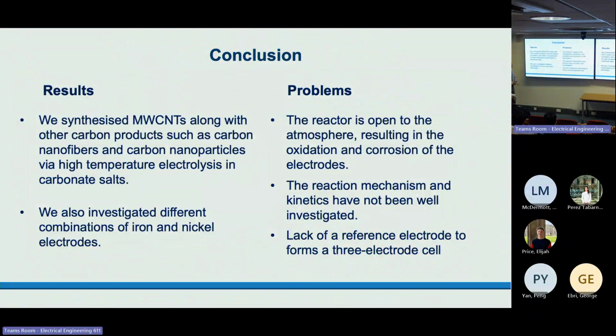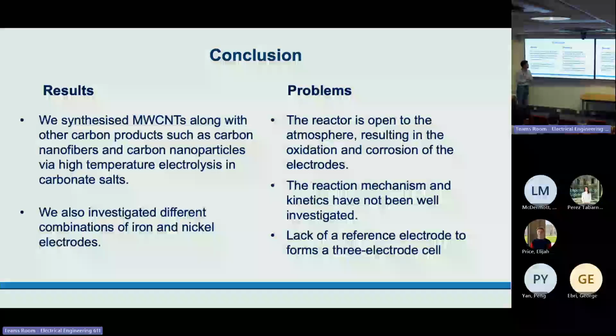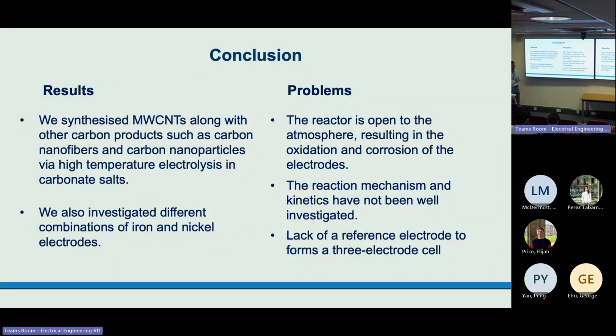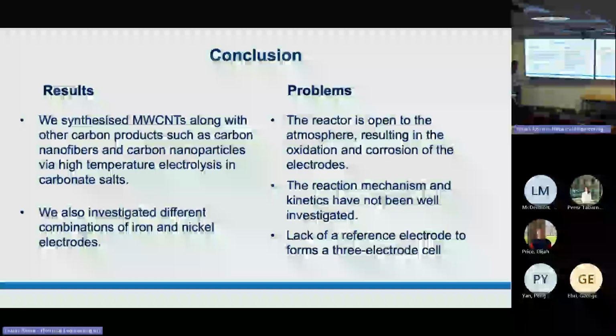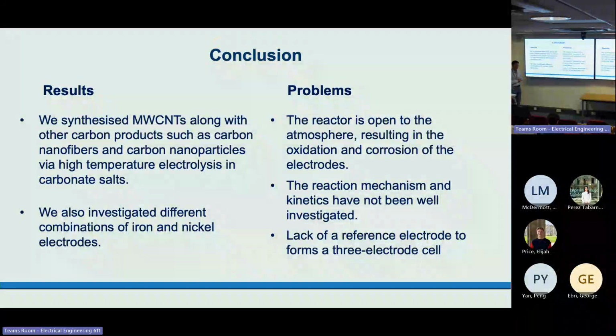So here is a conclusion. As a result, we successfully synthesized multi-walled carbon nanotubes along with other carbon products such as carbon nanofibers and carbon nanoparticles via high temperature electrolysis in lithium carbonate salt. We also investigated different combinations of the iron and the nickel electrodes.